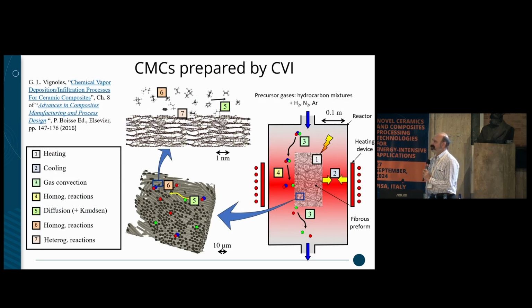Okay, so CVI is something that we already have been describing. So the main point is that your precursor gases, well, for example, hydrocarbons to create carbon, are introduced in that furnace with usually low enough pressure so that it can diffuse easily between the fibers here, and by heterogeneous reaction lead to solid deposit and also the evolution of byproduct gases.